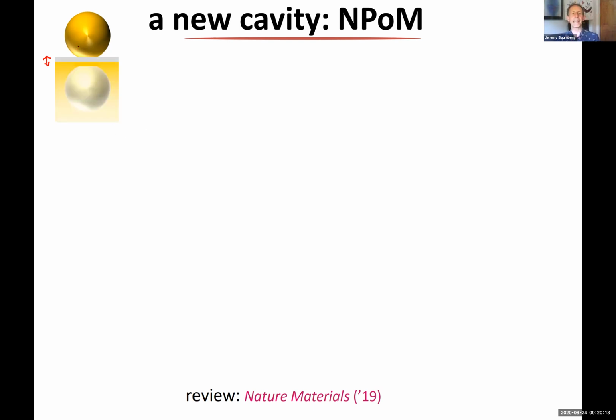But if I instead put the graphene on bulk gold and I bring a gold nanoparticle on top, then it works spectacularly well. And it actually depends on some undergraduate physics that you often learn. So you learn that if you put a charge above a bulk metal surface, then the electrostatic field here can be modeled with an equal and opposite negative charge, the same distance inside the material, and then you can get rid of your metal.